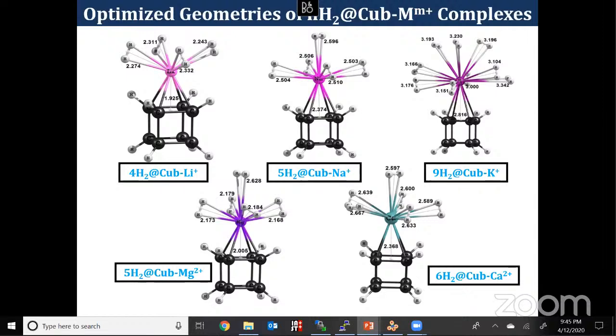But the one disadvantage is that the distance between the metal and hydrogen will increase. That means if we are really going to do a real study, from that point of view we can't use potassium, but we can use lithium or sodium. The distances are very small, less than 2.5 angstrom. That means it's strongly bound, but it's not chemically bound.